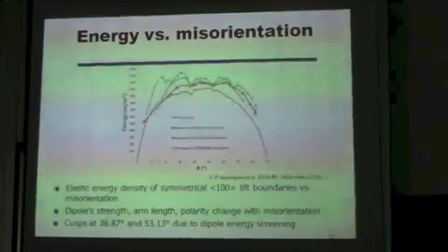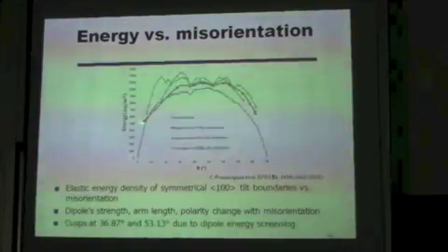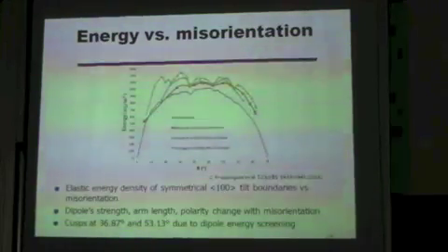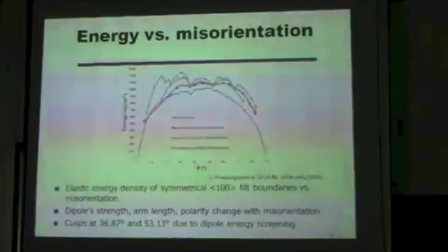Note also that the Read-Shockley energy saturates at this level after 10 degrees. So it's completely off track as of the high misorientations here. We even have the cusps that are observed at these 2 angles here.